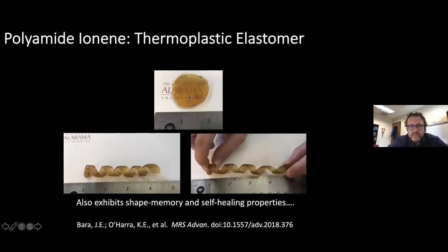So initially what we saw then was that, unlike the polyimide, which was strong but brittle, this was much more rubbery. So it had some excellent resistance to impact. It had elasticity, but it was still quite strong. So here, this was Katie making this as a coil and showing the stretchability of it, and that it will come back like a spring. So again, this is quite an interesting material in what it does.